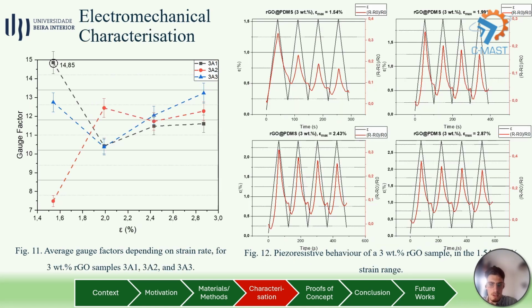In the cyclic tests, all samples underwent 4 bending cycles at a maximum strain rate between 1.54 and 2.87%, and 3 wt.% rGO samples showed us a maximum average gauge factor of 14.85, while also exhibiting the most typical electromechanical behavior of all, with excellent linearity and low latency. However, despite the signal having these characteristics, a relative electrical resistance leakage was observed, something common to all tests and which will be discussed later.